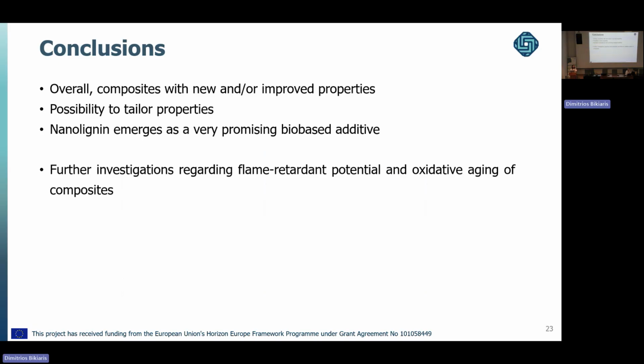So overall, we see that using lignin, we can have composites with new or improved properties compared to the neat polymer matrix. We have the possibility to tailor to some extent the properties of the material depending on the type of additive we use and its content. Nanolignin has emerged as a very promising bio-based additive. We have obtained promising results regarding flame retardancy that still need to be further investigated. Also, the oxidative aging of the composites needs to be further investigated. Since we saw that lignin can to some extent show antioxidant activities, it would be interesting to see how aging is affected by the presence of lignin or modified lignins.